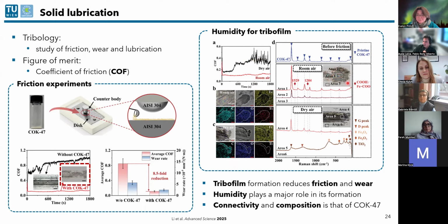When we did, for example, XRD, we saw that there is a complete amorphization. However, what was key was that we did some EDX and Raman spectroscopy, and we could see when we had the normal humidity, the composition of this tribofilm was that of COK-47. So we had titanium in this wear track, we had oxygen and carbon in this area, this colorful area. But when we had dry air, first, it was a way deeper scar. And second, there was almost no titanium there anymore. So that means titanium got lost and this tribofilm wasn't built.